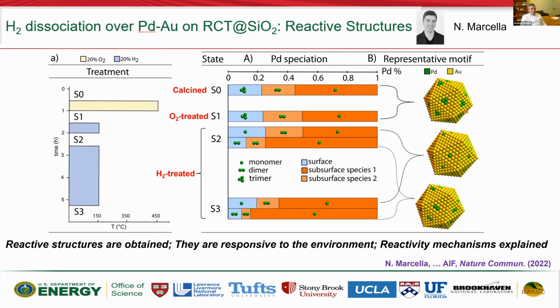So with that, we can say that we obtained reactive structures. We say that they're responsive to the environment because they change dynamically in response to their environment. And in principle, we can plan different reactions depending on what catalytic species we put on the surface. And if for some reactions, monomers are more active than dimers, we know how to do that. And so we can use the same catalyst and tune it for different reactions. And we can monitor in reaction conditions what catalytic species are on the surface by using these techniques. So that's maybe a very futuristic goal, but conceptually it's doable.